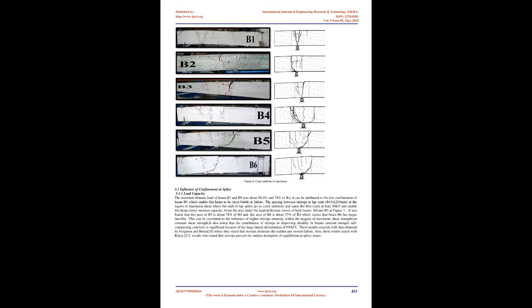2.1 Test specimens. The proposed test program has been designed to fulfill the following criteria. 1. Suppress the bending failure mode. This is because the program discusses the behavior of bond and shear failure at support at maximum shear. 2. Get the bond failure of the lap splice before yield of bars. 3. Evaluate the applicability of various lap splice equations, in different building codes and standards, for calculating lap splice in self-compacting concrete beams. Table 1 gives a complete description of the test specimens that includes the variables.